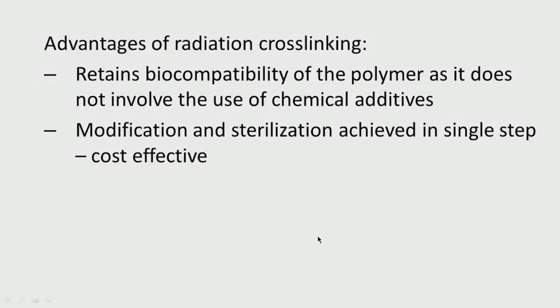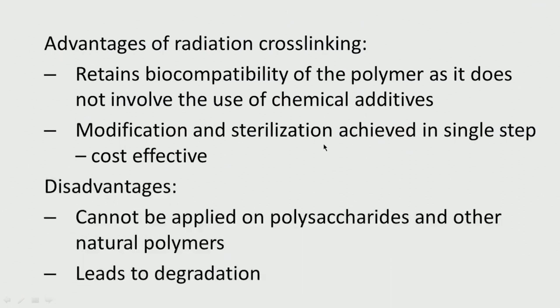The advantages of radiation crosslinking: it retains biocompatibility of the polymer as it does not involve chemical additives, avoiding modification of functional groups, reactivity, hydrophilicity, or surface energy. It also achieves modification and sterilization simultaneously, making it cost-effective. Disadvantage: it cannot be applied to polysaccharides and other natural polymers because biopolymers will completely disintegrate, leading to degradation.